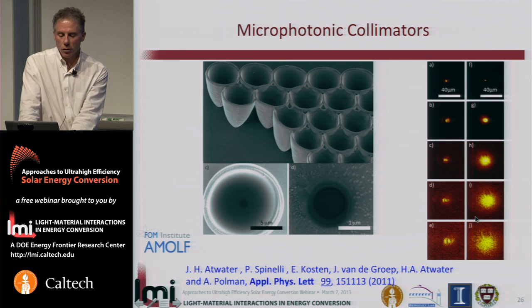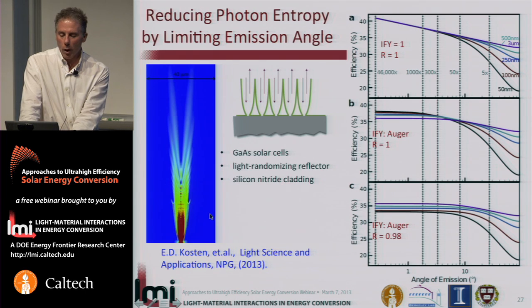And this collimation of the light leads, for high radiative efficiency, to increases in the open circuit voltage and efficiency of the cell. If the internal radiative efficiency could be 1 for all solar intensities, then this would be a very high efficiency exceeding 40%. We can't do that in practice because, for example, Auger recombination limits the radiative efficiency at high intensities. But indeed, efficiencies in the 30s% for single junction high radiative efficiency cells seem to be possible using this approach.